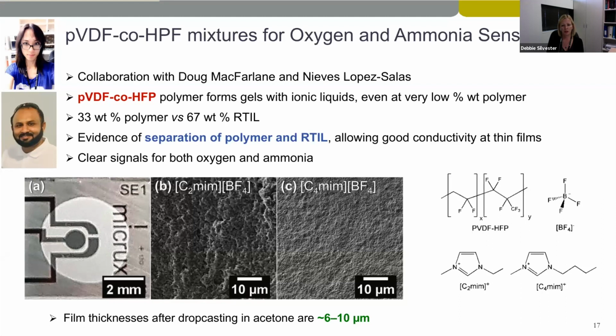And because we could go to these thin films, we can then do long-term sensing of gases because otherwise the response time would have been far too long for the thicker films. And for both oxygen and ammonia, we're able to get very clear signals in the voltammetry.